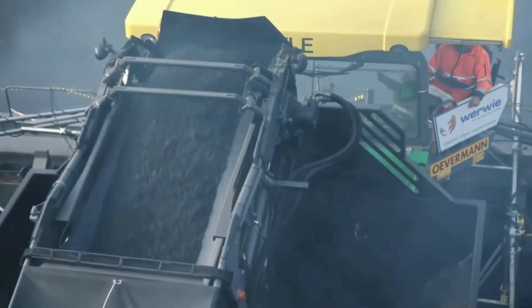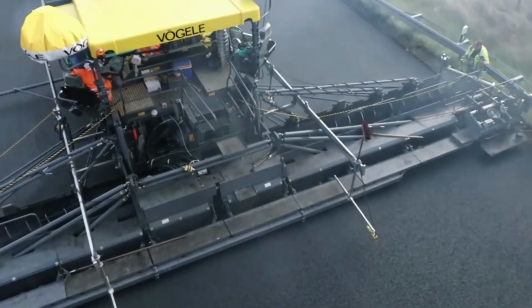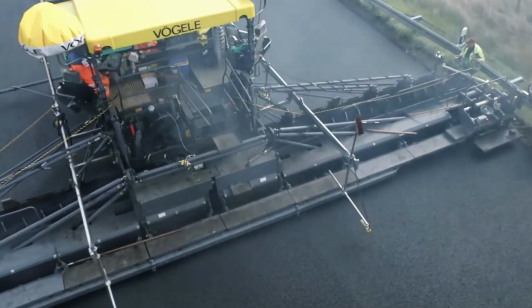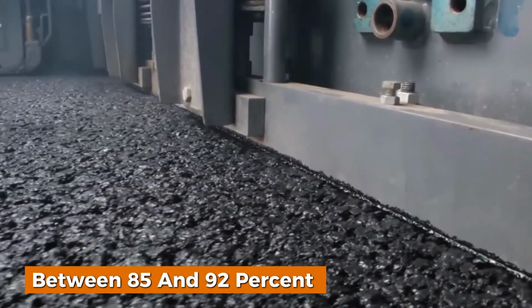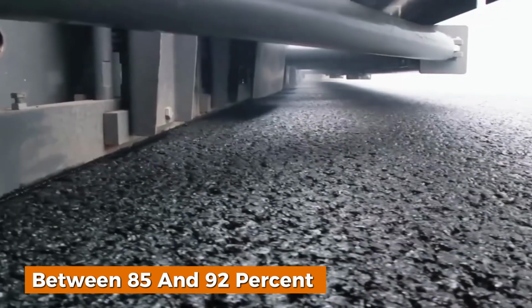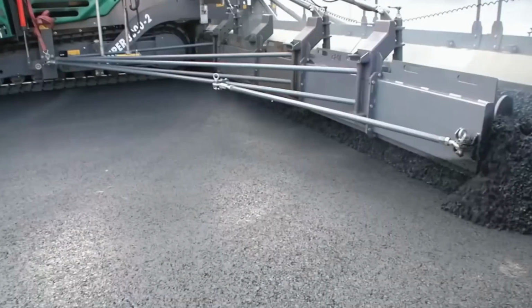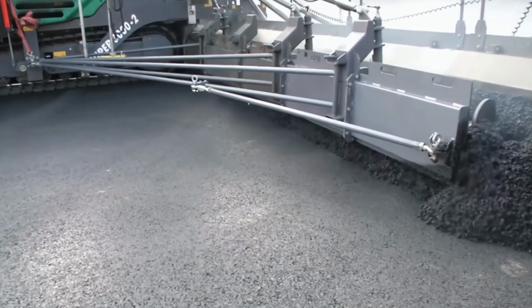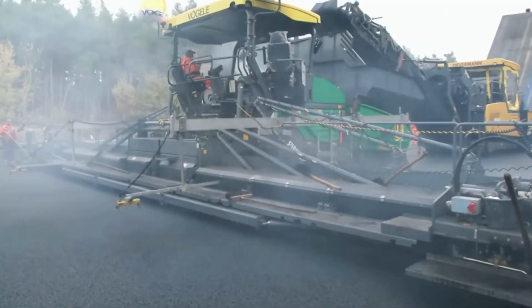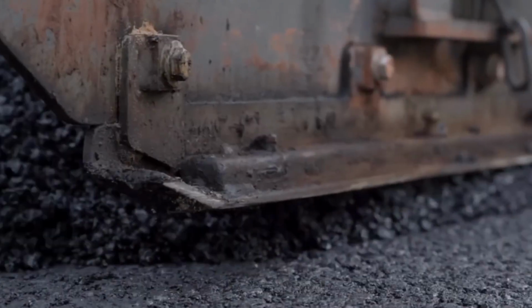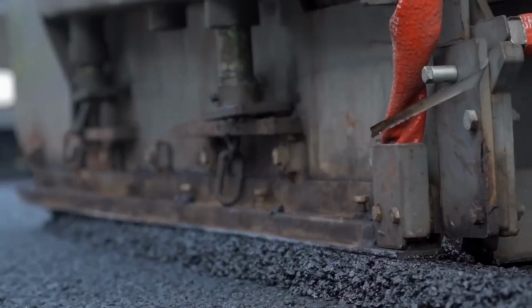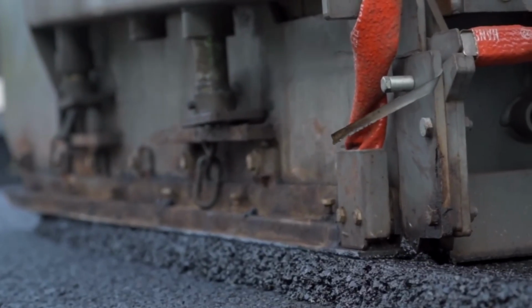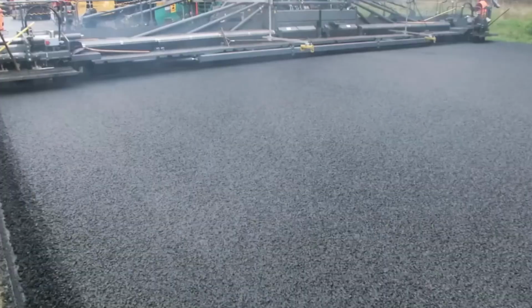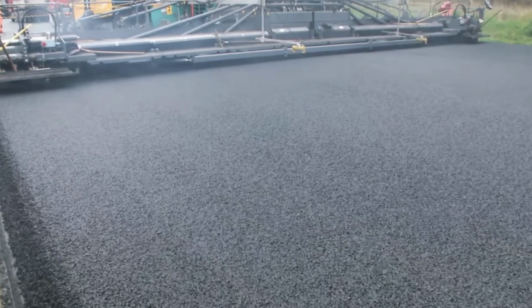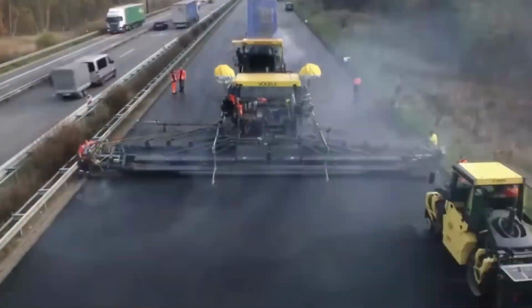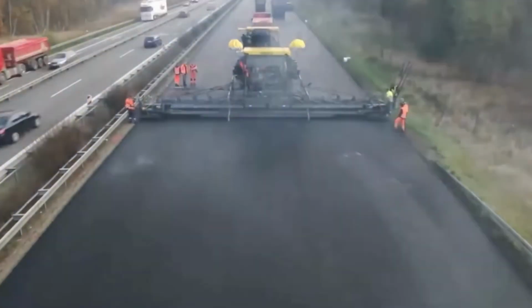The key action takes place at the screed, the vibrating tamping and pressing unit positioned at the back of the paver. While the asphalt is still extremely hot, the screed can achieve between 85 and 92% compaction. This allows the layer to be shaped, compressed, and smoothed in a single pass, setting the foundation for long-term performance. This approach is especially effective for surface courses such as stone mastic asphalt, which are typically only 2 to 3 centimeters thick and cool very quickly. Traditional vibratory rollers used on such thin layers can create cracks or ripples. Modern automatic screeds avoid this problem, producing a surface that remains smooth, evenly textured, and uniform along the entire stretch of road.